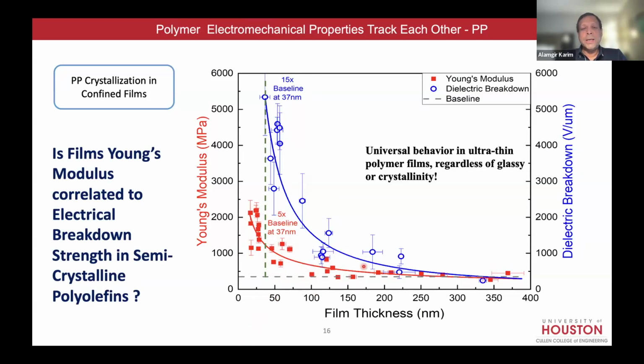So the modulus enhancement is primarily because of the high degree of crystallinity that orients. Okay, so this is only true for high crystallinity block polyolefins, I would say. I'll show you the next example. LLDPE, it actually drops, but the breakdown voltage still goes up. Okay, so these two are actually uncorrelated, even though they may appear correlated, they are not really correlated. So don't take the red, mechanical property is not correlated to the breakdown we think at this point.